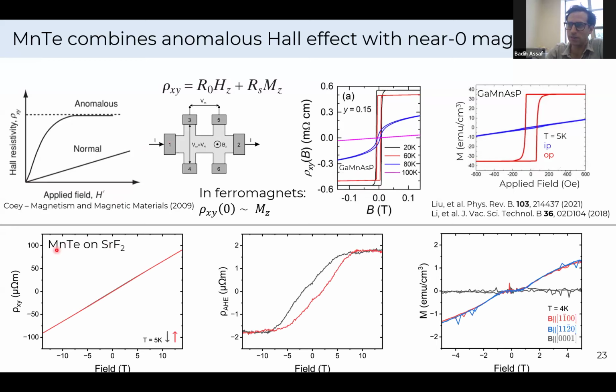You stick electrodes on manganese telluride, you measure it, you see this very strong linear Hall because MnTe is a semiconductor with a relatively low carrier density. You subtract the slope from this, and then you recover an anomalous Hall effect, allowed by symmetry. But what's surprising is that in that same sample, you go and you measure magnetization, and you see this plot that I'm showing you here.